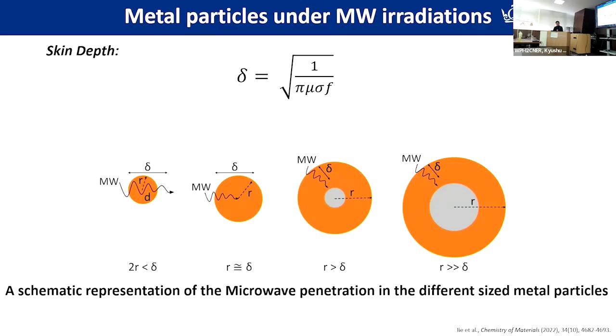In that case, if you imagine a 25 nanometer iron particle, it is way below the skin depth. So part of the microwave actually penetrates through, so it's not all absorbed and efficiently converted to heat or used for chemical reactions. If it's just equal to the radius of the particle, it's fine, but still not perfect. And what is best is about 2 times the skin depth of the metal.